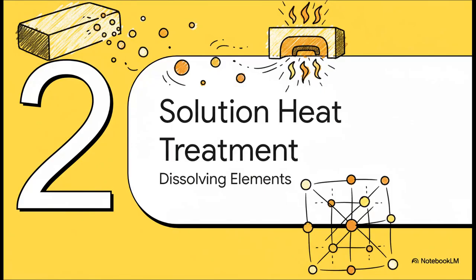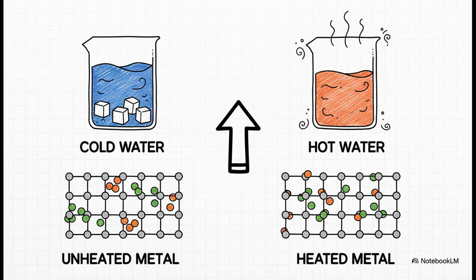The very first step is all about getting our ingredients mixed perfectly. To do that, we heat the aluminum alloy to a very, very precise temperature. We're talking somewhere between 515 and 575 degrees Celsius. This high heat is what allows the atoms of, say, copper or magnesium to completely dissolve and spread out perfectly evenly through the aluminum. And this is the perfect analogy.